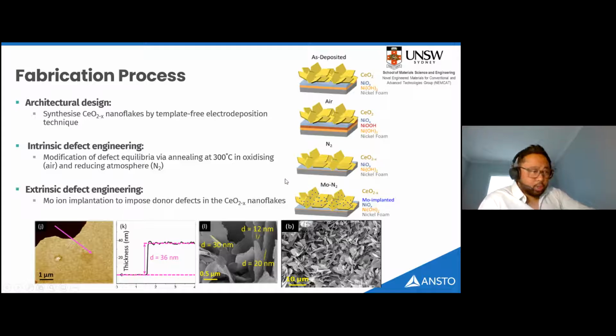And the figures at the bottom show AFM, the thickness. The ones on the left are from AFM, showing about 36 nanometers in thickness, and the SEM also a range of about 12 nanometers to 30 nanometers thick of those nanoflakes. Next slide, please.